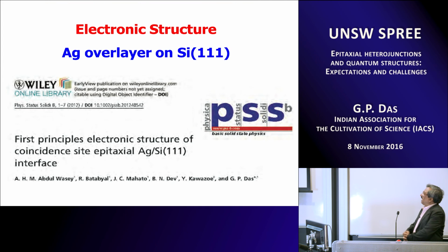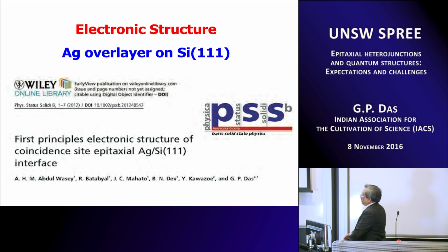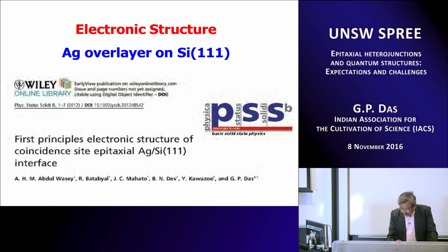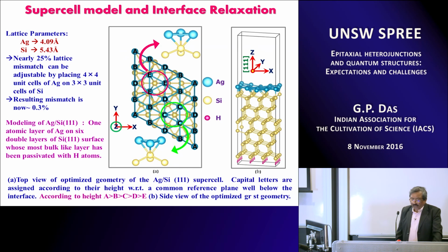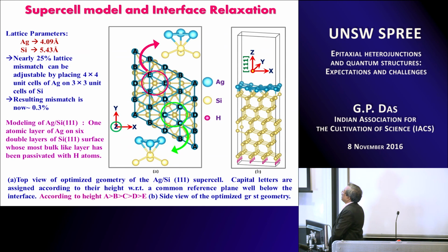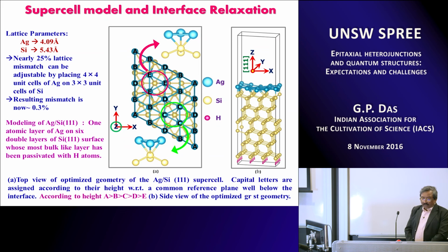Now I'll come to another example, which is not lattice matched like NiSi2 to Si, but is lattice mismatched. For example, silver on silicon 111. If you look at the lattice parameter of silver, it is 4.09 angstrom. That of silicon is 5.43 angstrom. This is a huge lattice mismatch, nearly 25%.